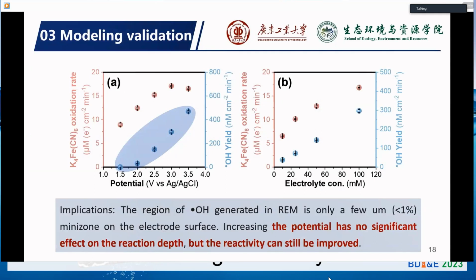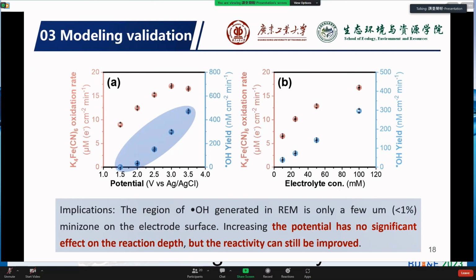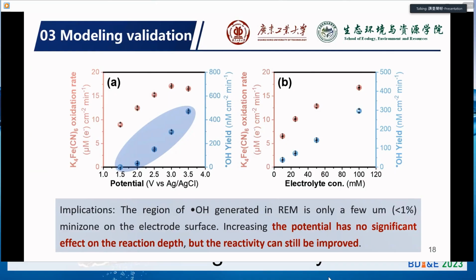Although when we increased the applied potential onto the REM there was no further increase of the reaction depth, this practice can still increase the reaction rate because it increases the charge transfer rate and the electrochemical activity. But essentially, the kinetics and the reaction depth are two different kinds of things.